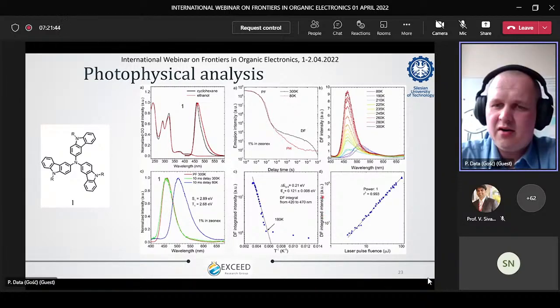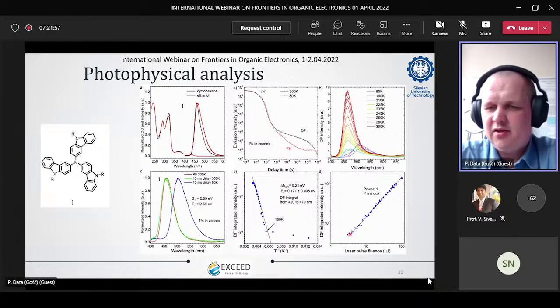We collect the delayed fluorescence emission, integrate our spectra, and get our intensity. We check how it behaves with increasing excitation energy, in this case laser pulse fluence. So we increase our laser energy and check how our emission increases. If the increase of this emission is in the power of 1, it means for one harvested triplet state we get one singlet state, and that means we have TADF.